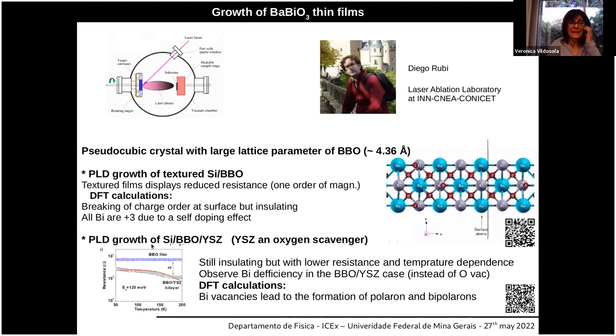Then they had the idea of putting yttrium stabilized zirconia on top of barium bismuthate, which is supposed to be an oxygen scavenger. So to see what happened in this case, if we take even more oxygen from the system, if it can bear such an amount of doping, and instead of taking oxygen out of this BBO, we observed that the deficiency was in bismuth. The yttrium stabilized zirconia induced bismuth vacancies.